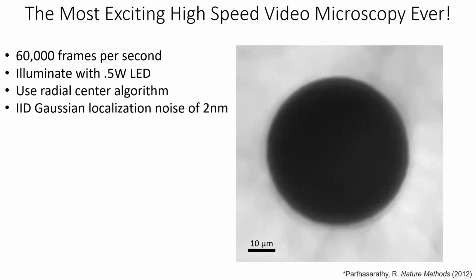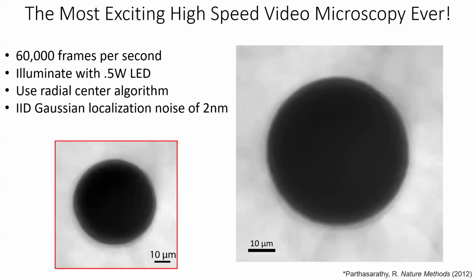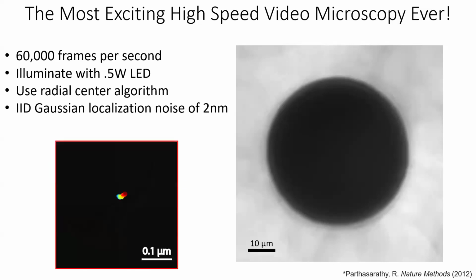We're able to localize them down to about 2 nanometers, but then their noise is IID, so we can even do better. I'm sure everybody loves looking at high-speed video, so I'm sure you're just absolutely entranced by this. What we can see is we can take this whole video and track it, and we can see the motion of the particle. And from this, we can make amazing measurements. The reason is as we continue to zoom in, we can actually track this 50 micron particle on length scales of nanometers really, really accurately.